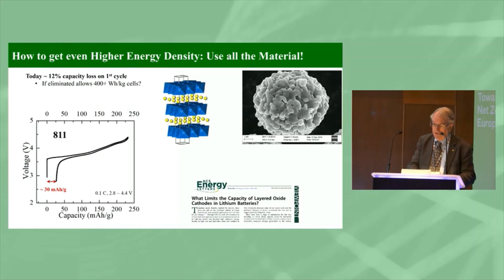So let's look at the first problem we can address, and that's what we call the first cycle loss. All these materials, when we charge them, so here's the charging curve, we've gone up to about 4.4 volts, commercially they're about 4.3, and this is 80% nickel, 10% cobalt, 10% manganese. We discharge down the same curve, you never get all the lithium back in again at room temperature. This is what we call this first cycle loss, and this is what we've been trying to solve.